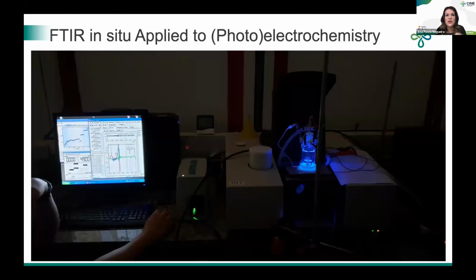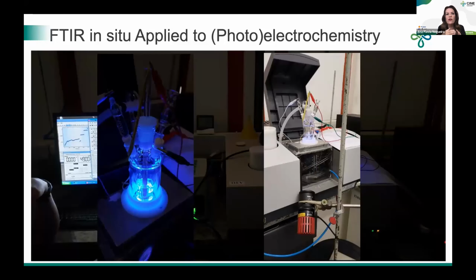So today I'm going to present some data on the infrared in situ applied to photoelectrochemistry. And then you can say, okay, but this is very common. Of course, it's very common to have in situ infrared coupled to electrochemistry, but not to photoelectrochemistry. It means that together with in situ infrared, we are also shining, as you can see here on the bottom, we couple a solar simulator. So it means that you can get this in situ infrared in the dark, and also under, for instance, one sun conditions. I think this is the novelty of this technique that we developed here in Campinas.